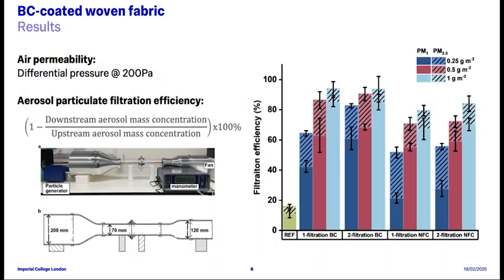We then test these bacterial cellulose coated woven fabric samples for air permeability with a benchtop device and the particulate filtration efficiency with an in-house built wind tunnel, where we place the testing sample in the middle of the wind tunnel, and during testing, sodium chloride particles will be generated as a challenge particle, and the ratio of sodium chloride mass concentration upstream and downstream of the sample will be taken as the particulate filtration efficiency.